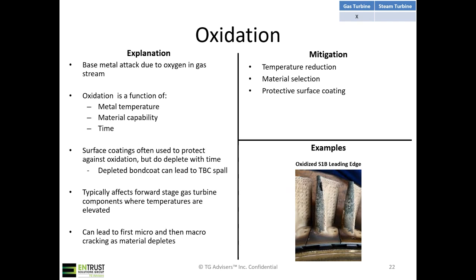Oxidation is base metal attack due to oxygen in the gas stream. This is predominantly a gas turbine failure mechanism, obviously because the temperatures are so high in gas turbines. Oxidation is a function of predominantly metal temperature as well as material capability and time. You won't see it within the first couple hours of operation, but over time, the material will get burned away if it's too hot inside the flow path.